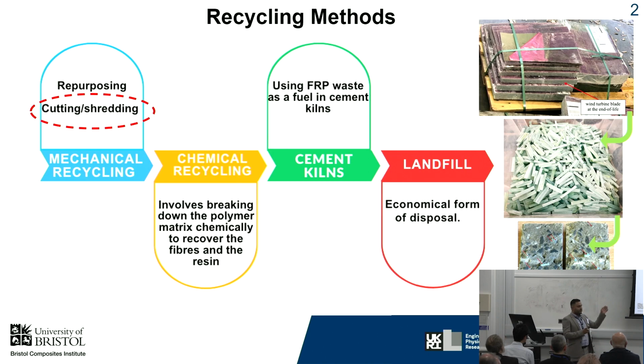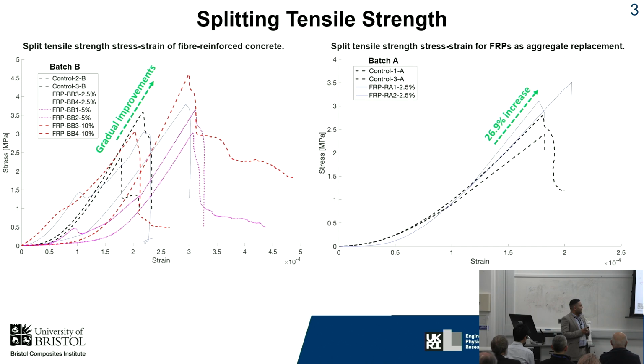Concrete itself is a very complex mixture as well. Any change in the mixture will cause different mechanical properties. So we established two different batches. In the first batch, A, we replaced the aggregate with the FRP needles, what we call an aggregate replacement. In the second batch, B, we just added the needles into the mixture, to study both effects. For batch A, we had a nearly 26.9% improvement in tensile property, while batch B, the addition only, has a gradual improvement.